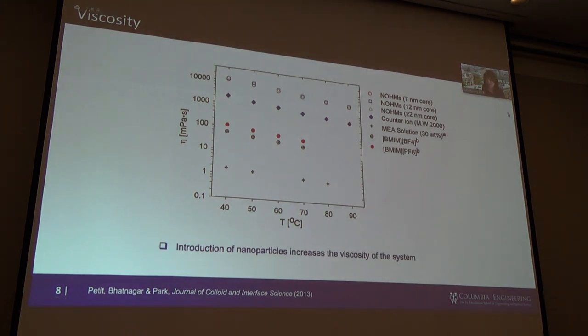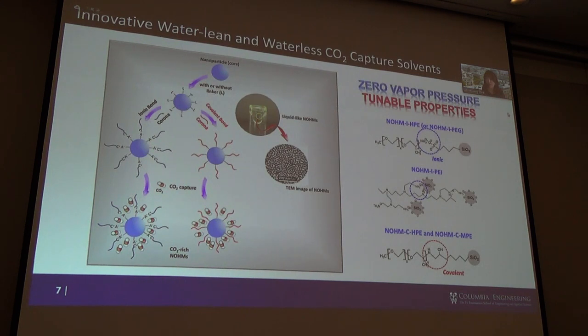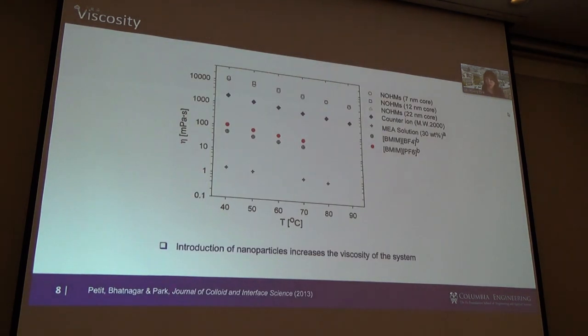And we actually found these materials capture CO2 very effectively and very selectively. But one of the challenges, as you saw in the picture before, is that you actually have to have a large amount of these materials produced, not only synthesized and purified, and then put into large reactors. So one of the first things you have to think about when deploying these in a large-scale reactor is mass transfer. And that's linked to viscosity.